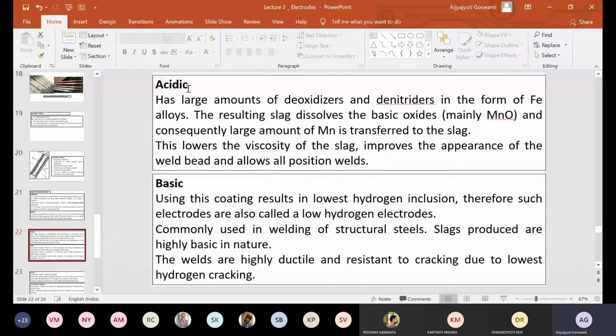Okay, acidic coating. They have large amounts of deoxidizers and denitriders in the form of iron alloys. The resulting slag, the slag which is formed, dissolves the basic oxides, mainly manganese oxide, and consequently a large amount of manganese is transferred to the slag. These types of coating, acidic coatings, are specifically done for carbon manganese steels, where manganese is in large quantity. If the manganese is not excluded, it may form other compounds and become part of the weld deposition, and then it may create some problem in the welding. So some manganese has to be precipitated out.